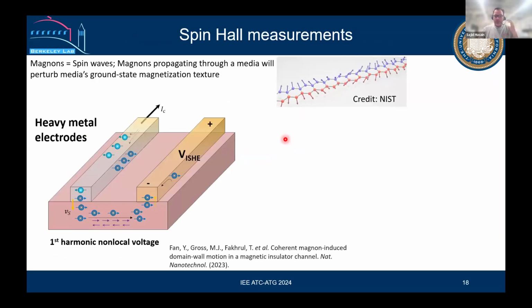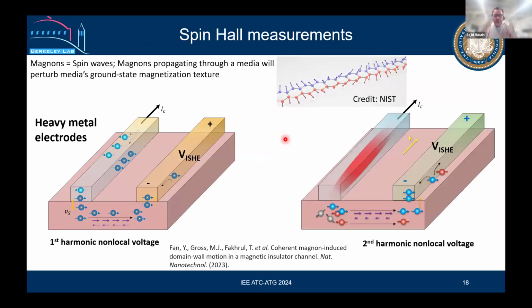So the method that I'm going to explain, as I mentioned earlier, is a non-local method in the beginning. I will try to show you some data. We have two methods to measure our output voltage. First is spin Hall effect driven. In one of the electrodes, you supply some current, and because of the spin orbit coupling, spin charge to spin conversion, you have polarized current here. And because of the spin accumulation, you transfer the angular momentum to the magnet here, and it travels through the whole material, and you can pick it up as an inverse spin Hall effect voltage, the output.